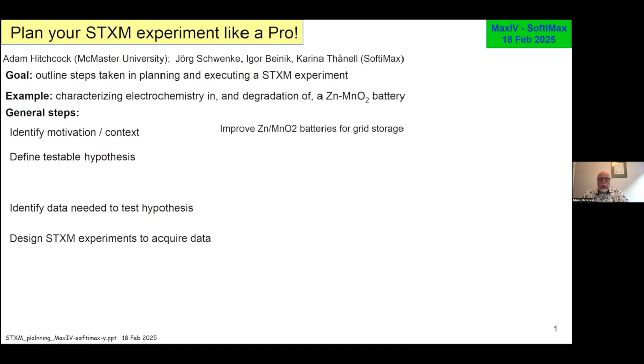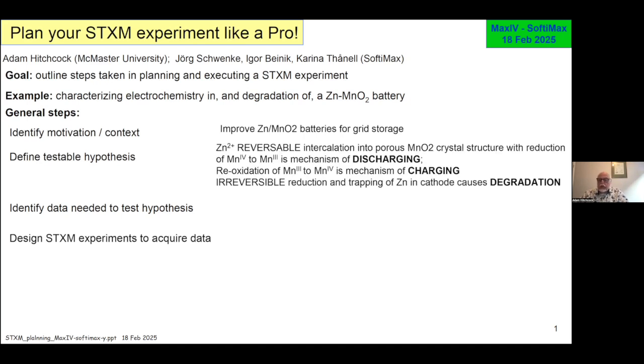So the step of defining a testable hypothesis, in this case, if you look at the literature, there's some question exactly as to the active chemistry and electrochemistry that's going on. What is the mechanism whereby the chemical potential of the charge system can be released to create currents in external circuits, and how do you actually recharge the system? What's the chemistry involved in that? And also what's the chemistry involved in degradation? And because these questions can be couched in terms of identifying oxidation states and chemical species, in particular of the manganese species present in the batteries, this is a system where STXM is quite relevant because the manganese edge is a nice edge for STXM to work on.